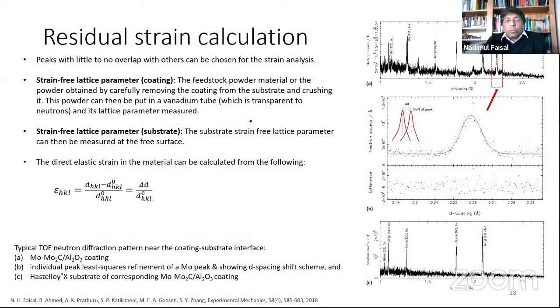Now, as soon as you do the scattering, you will come across a spectrum like this, where you have d-spacing or time of flight on the x-axis, and then you get counts or intensity, and you get these peaks. You may have seen this in X-ray. In neutron, you also get similar peaks. So you need to know about each of those peaks, because you will be analyzing these in much detail. For strain, you measure the peak, and then you measure another location or another reference sample, and you will observe some shift happening. That shift, either this side or that side, gives you the measure of a strain.